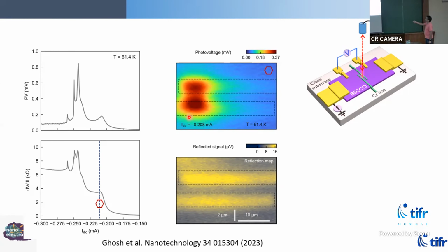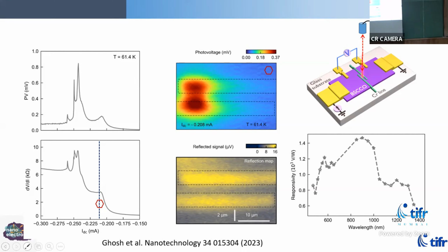And what we see is that the photo response is peaked right at this point. This is the region where the hotspot is. So when we shine light at this place at a particular bias, it's extremely sensitive to the light, to the extent that we can get very large responsivity across a relatively broad range of wavelengths. And this is at about 60 Kelvin, which is already pretty good. What we need to improve is the electronics that we use to amplify the signal and reduce parasitic capacitance so that we can do it as fast as possible.